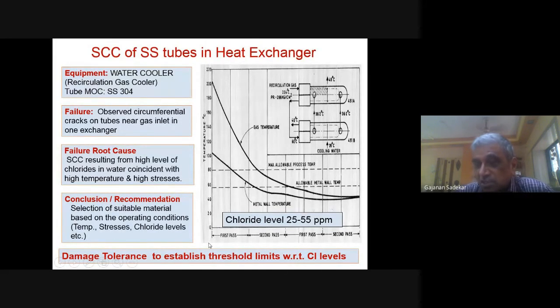Then I did a literature search, and I found Japanese people have published, for stainless steel tubes, specifically for heat exchangers of different types, what the chloride levels in the water should be. They have given the threshold levels, and I plotted those threshold levels. Can you see this particular threshold level here? The allowable metal wall temperature and allowable process temperature, and a chloride level of 20. Based on the chloride levels, because chloride levels were 25 to 55 we found, as I collected data on the water chemistry, and chlorides were as high as 55.